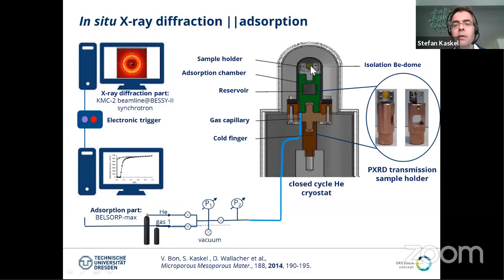The sample is located here inside a beryllium dome covered chamber, and this is basically our volumetric cell that we normally use in the adsorption experiment. So this is our volumetric receiver where the sample is located. You can also put some excess of the sample in this reservoir. And here the sample can be put into the synchrotron beam. And in this way, you can analyze diffraction patterns and follow the transitions in situ.